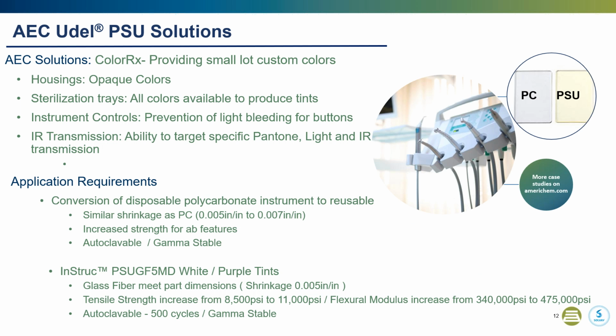Our application here is a reusable version of an existing disposable polycarbonate surgical tool in transparent colors. The requirements included maintaining similar shrinkage as the polycarbonate, increased strength and flex modulus, and being able to survive 500 steam autoclave cycles. We came up with 5% glass-filled PSU.